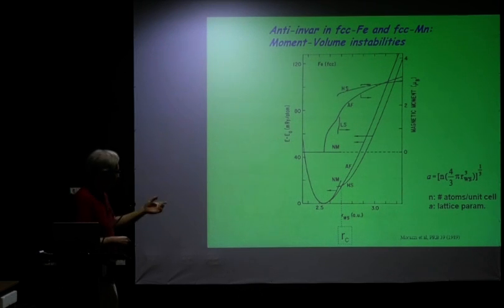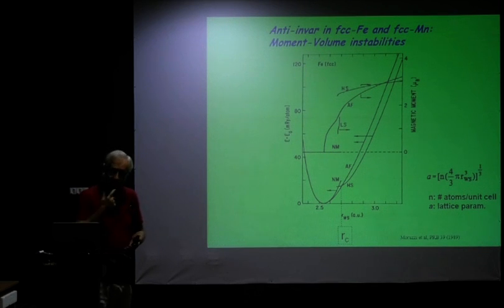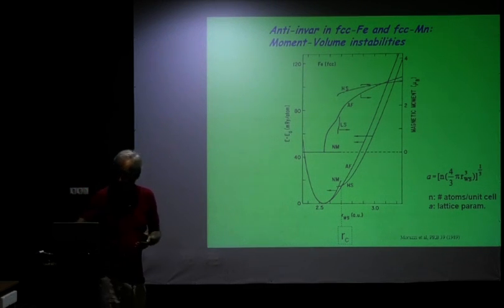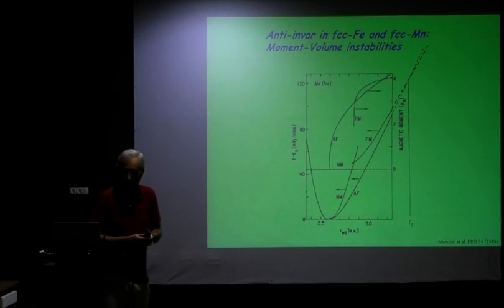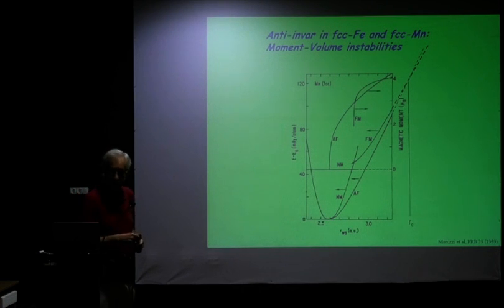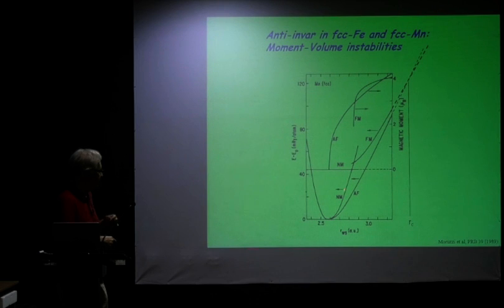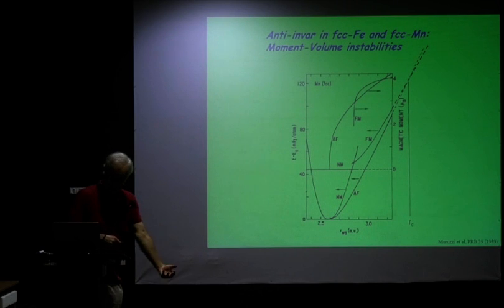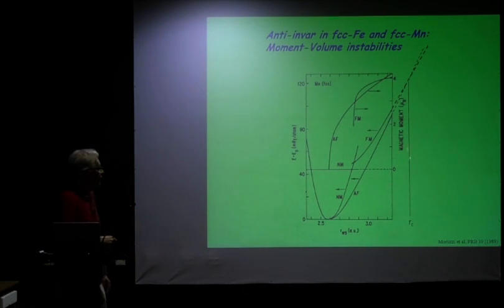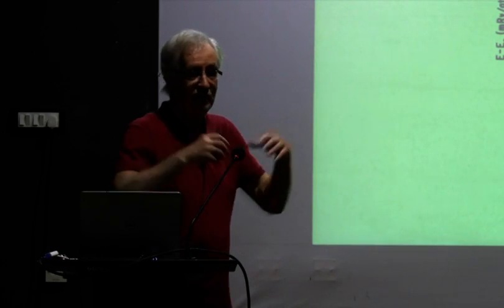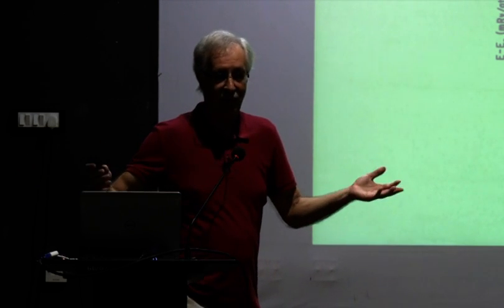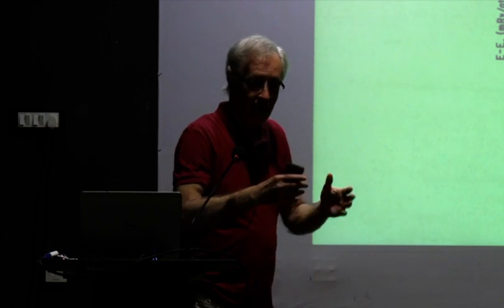Now, before we go into any comparison with real systems, let's look at Fcc manganese and see what these people have done. Fcc manganese shows basically the same thing, except that in the range of the calculations here, the antiferromagnetic state is the lowest energy state. So Fcc manganese is antiferromagnetic. And then when you go to very, very high volumes, it is only then that the ferromagnetic state has a chance to be stabilized. So you really have to expand manganese before you can make it ferromagnetic,